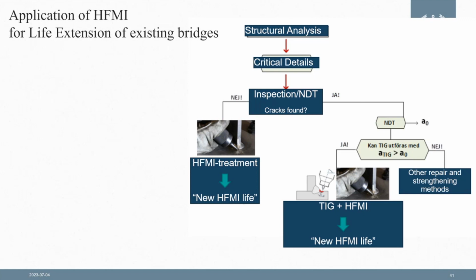In principle, the idea of using these methods for fatigue life extension is that you have an existing bridge, you do a structural analysis, you identify the critical details, and you inspect with some kind of NDT. If no cracks are detected, then HFMI treatment can be used, and one can assume a new HFMI life or fatigue resistance. If shallow cracks are detected, and these cracks are shallow enough to be remelted by TIG dressing, then TIG dressing followed by HFMI can be used to get a new HFMI life. Otherwise, of course, another method of treatment, repair or strengthening needs to be used.